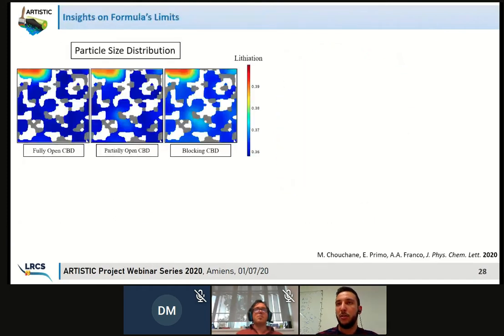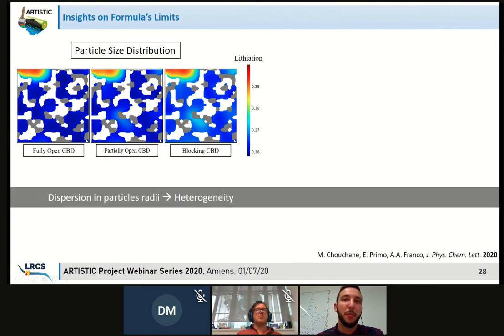But it will be more clear, I think, in 2D view. So here is a slice at the given point of the GITT simulation for each different hypothesis, where you can see that there is a dispersion in particle size radius. For instance, this given particle here is obviously smaller than this big one here, and it leads to higher heterogeneity in the bigger particle, because you can see that this big size particle is the one where there is a steeper gradient of concentration, whereas overall it's more or less homogeneous.